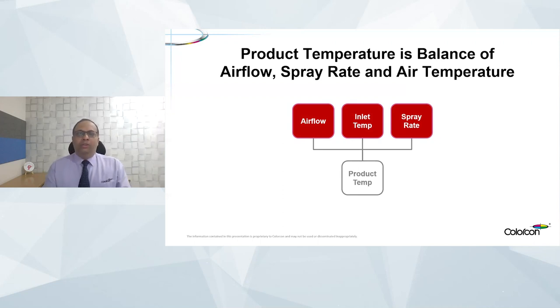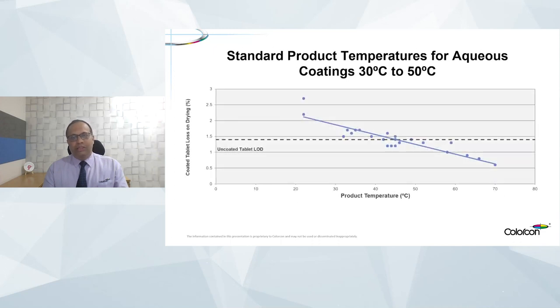They are pretty simple. Everybody who has done coating at some time or other in different equipment would be able to relate to this, but it is important to look at all three together and understand how they impact the product temperature. The reason product temperature becomes important is that it is independent of the scale, as well as specific to the product which is getting coated. We'll talk more about it a little later, but let's look at the product temperatures that are generally followed for aqueous coatings. They can range somewhere between 30 to 50 degrees Celsius, depending upon which type of coating you are applying and which substrate the coating is getting applied on.